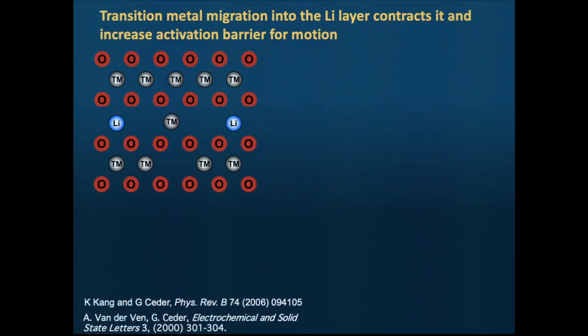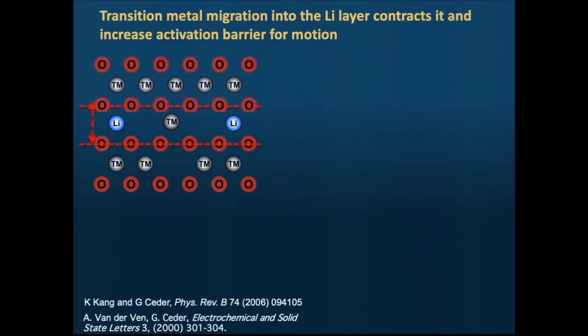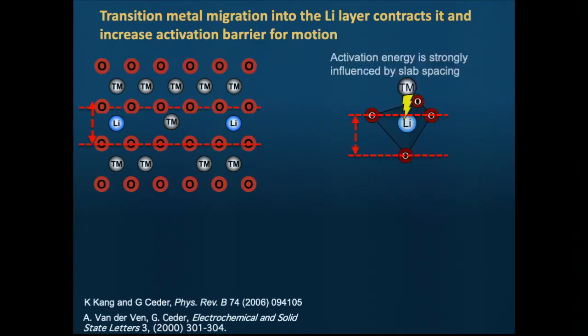And why is that bad? Because the transition metal has higher charge than lithium, it's 3+ or 4+, it pulls the oxygen layers closer. So it essentially densifies the structure. And what that does is increase the activation energy for lithium motion. And the reason is quite simple. This is essentially an ordered rock salt, so it's an FCC packing of oxygen. The cations sit in octahedral sites. And to migrate from one octahedral site to another octahedral site, they have to go through a tetrahedral site. That's just the crystallography of FCC.